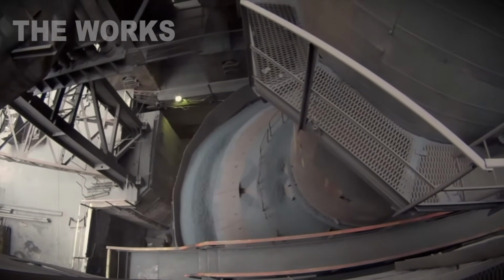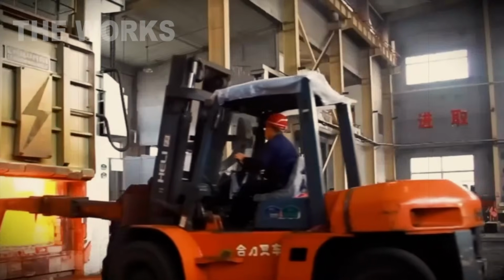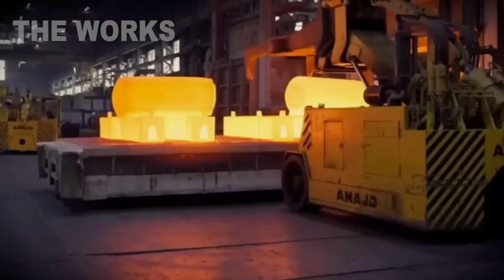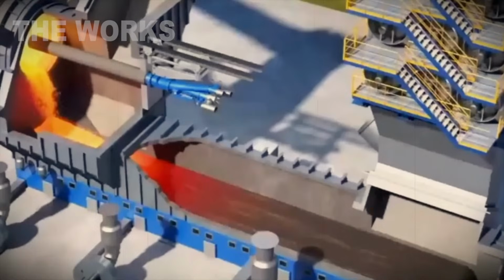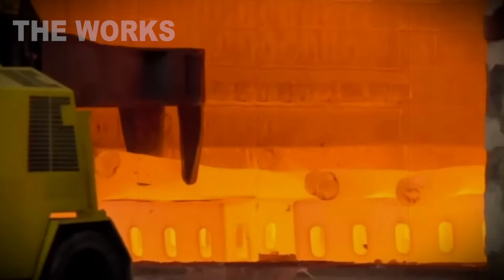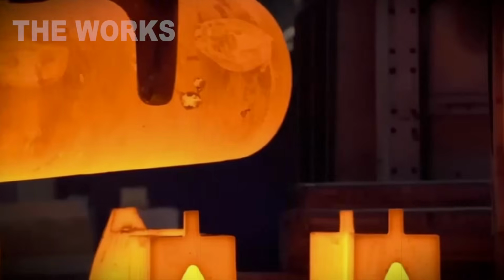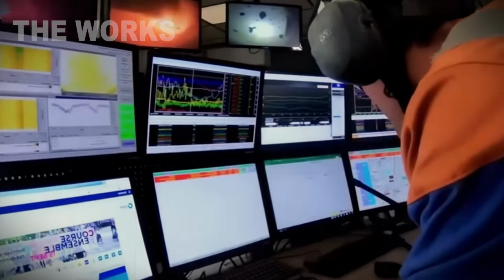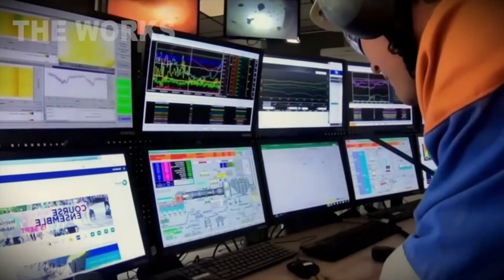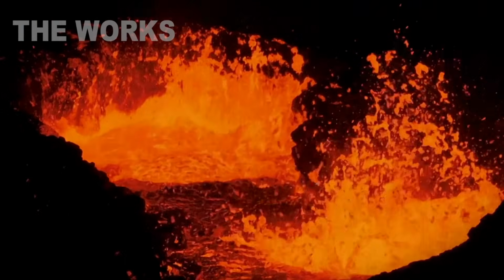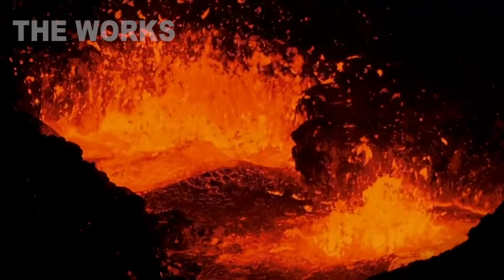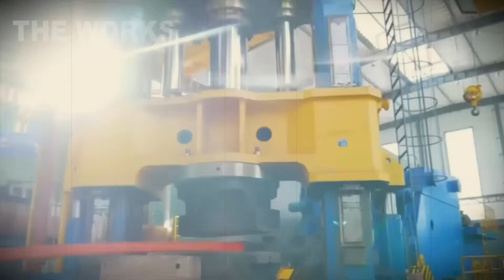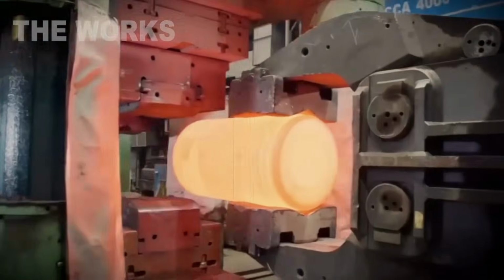Blast furnace smelting. Pellets are loaded into the blast furnace. The furnace stands 105 feet tall. The throat diameter, 40 feet. The hearth diameter, 26 feet. Furnace volume, 42,000 cubic feet. Loaded in layers. Pellet layer, 3 feet. Coke layer, 20 inches. Limestone layer, 8 inches.